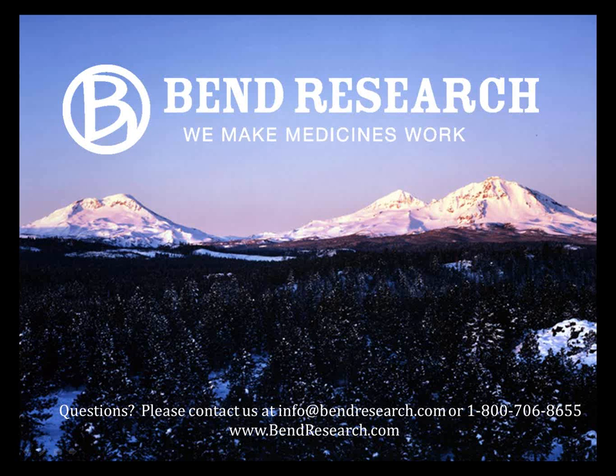We do have GC headspace analysis in-house to monitor, if we are going to use an organic solvent, what that actually looks like from the powder standpoint as well. We have used those systems Tim was mentioning. We can use those again, but we try to shy away from using organic solvents with biotherapeutics unless there's an obvious process or solubility driver that pushes us in that direction. And if we do end up going that direction, we can watch that over time and regulate those concentrations. Yeah, and just for case study 3, for example, it was a combination of an aqueous organic solvent blend.